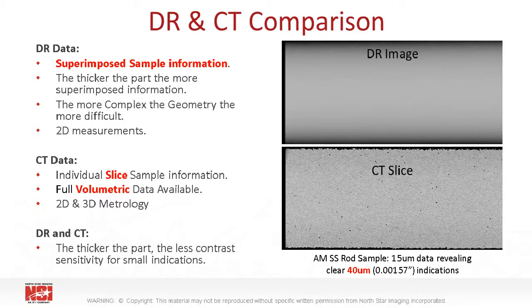On this slide, we show a DR image on the top and a CT slice on the bottom. The DR image on the top was actually one of many of the images that was used to generate the CT slice on the bottom. However, the microporosity that we see on the bottom, on the order of 40 micron in size, or roughly 1.5 thou, are not even visible in the DR image,